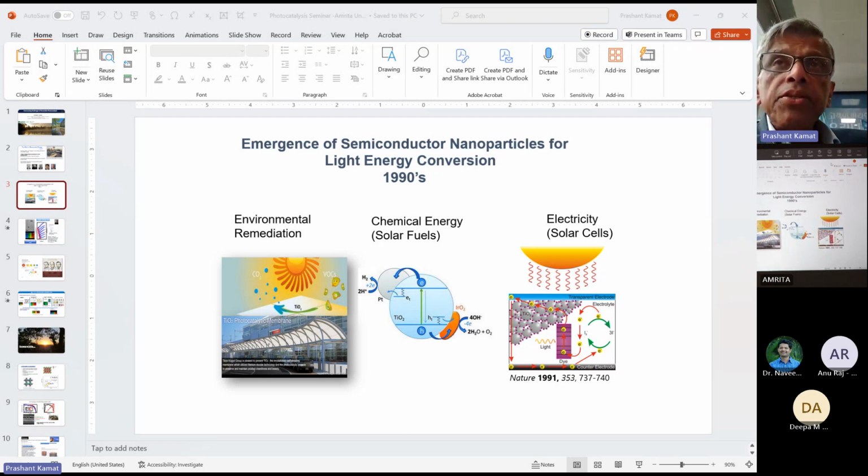People thought it was a good one to make because you can make non-lead based material. But so far, these kinds of materials are not very photoactive. You can try it. You can make cesium lead bromide nanocrystals and just add some gold bromide, and it will right away exchange, and you get a dark colored solution. If you add lead bromide, it reverts back because it kicks out. It is a metal ion exchange, but it is a different structure than the original structure.